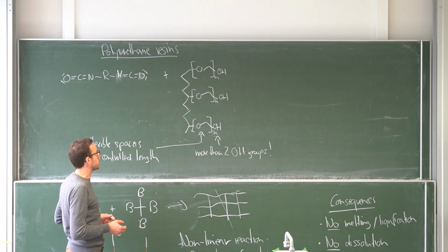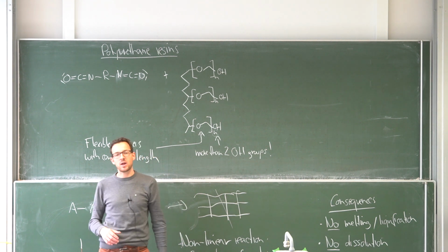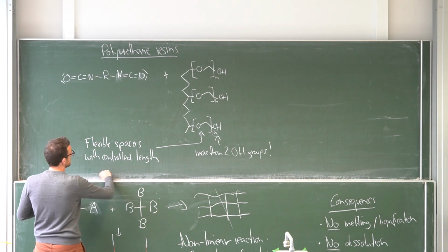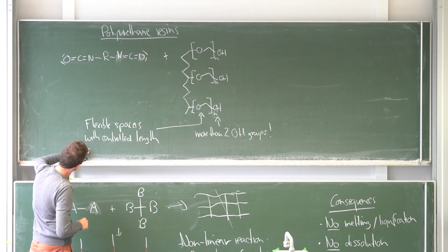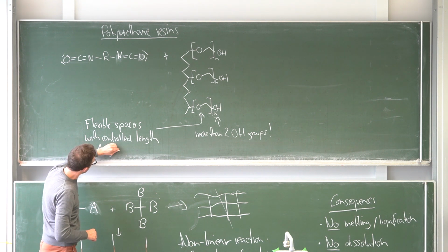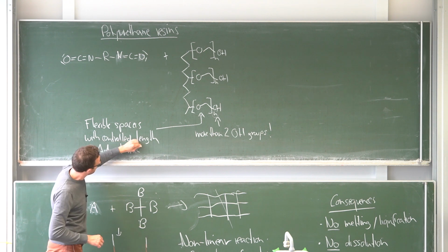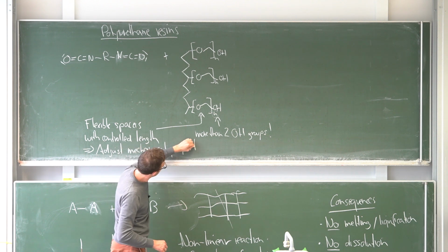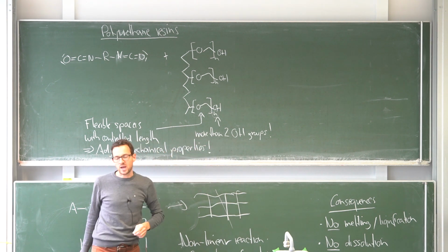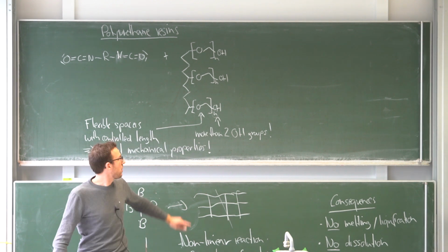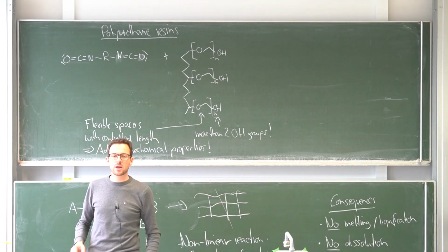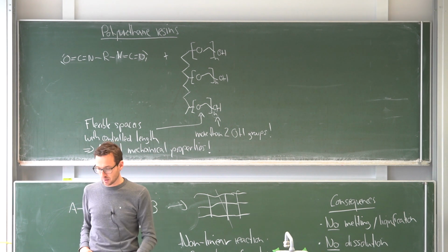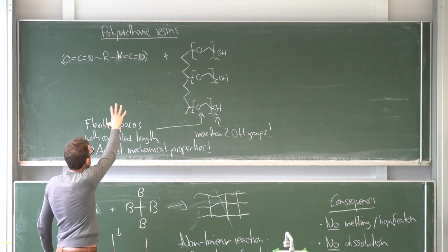And of course, if we want to make something really hard, we go away from such a material that has aliphatic chains and we replace it by something aromatic to make something really stiff and really hard. But these flexible spacers with controlled chain length, we can use to adjust or control the mechanical properties. So the mechanical properties are pretty much always hidden in fine details of the molecular structure. This can make a difference from the stiff bicycle helmet to the soft princess on the pea mattresses, okay, that we discussed in the very beginning. And again, of course, this is true for polyurethane resins.